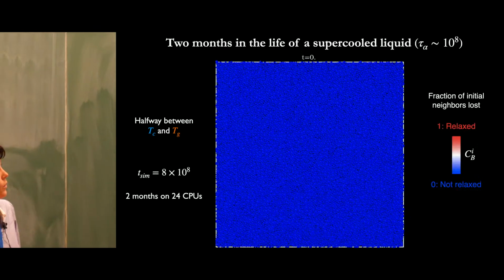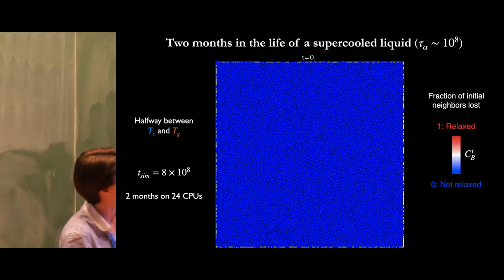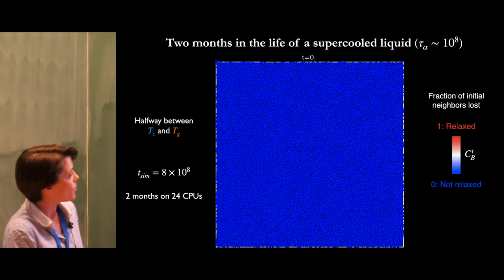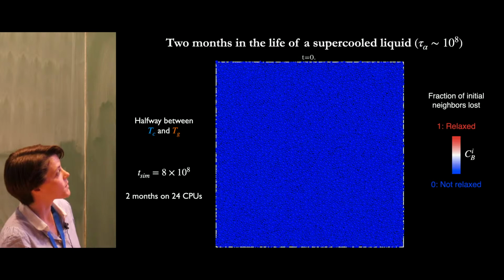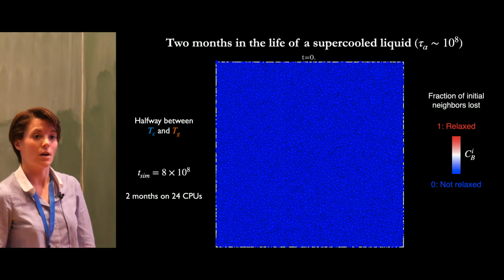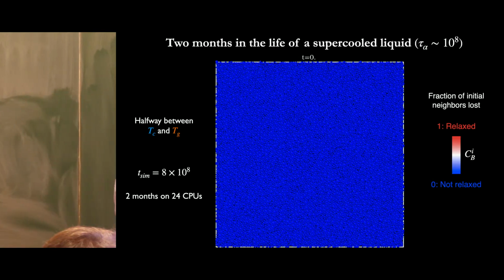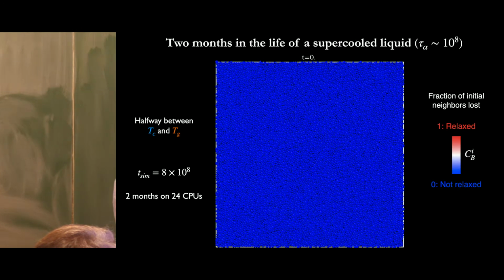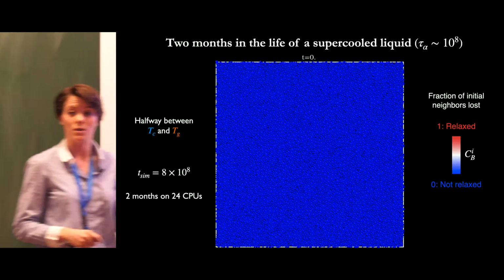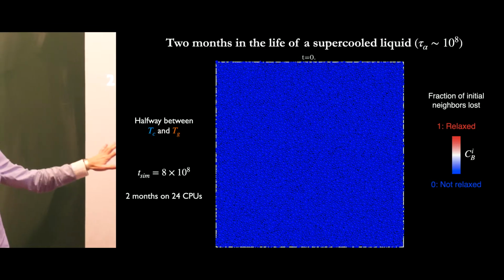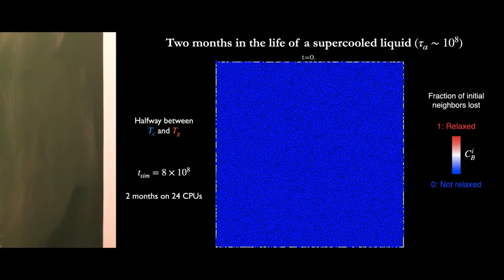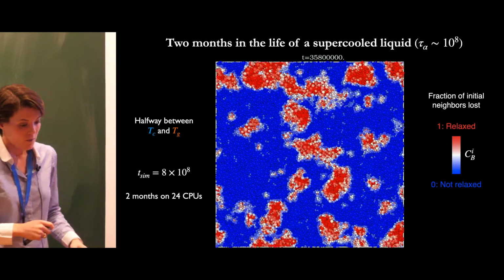I'm going to show you the movie of the dynamics. Here, this is the same configuration. I'm going to simulate this over extremely long times, actually 5, 6 tau alpha in this case. I'm going to show the dynamics as we go through the simulation in terms of this indicator here. This indicates the fraction of initial neighbors in the structure that the particle has lost. So it's just telling you if the particle has relaxed or not. Blue particles correspond to the initial structure, and red correspond to a new structure. So if I show you the movie,